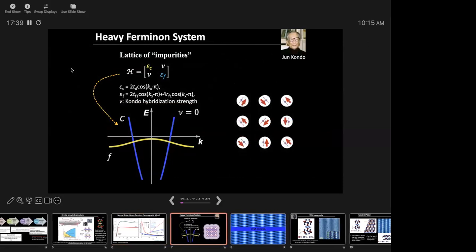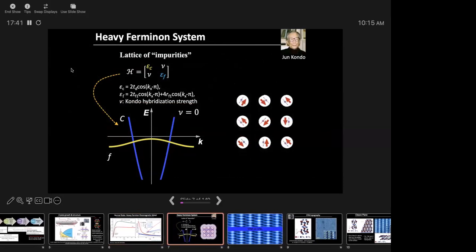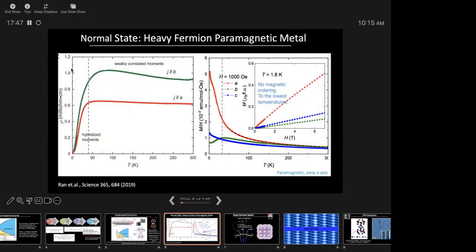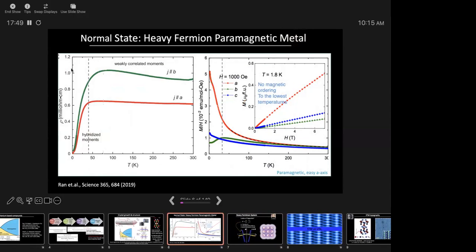So it's a paramagnet. Okay. So just to remind you, before I show you STM data, in your previous paper, the a-axis susceptibility has a shoulder at around what, 20K? Yes, there is a shoulder. They don't know what that is. Yeah, and tellurium NMR is not saying anything about this change in the tellurium Knight shift either.